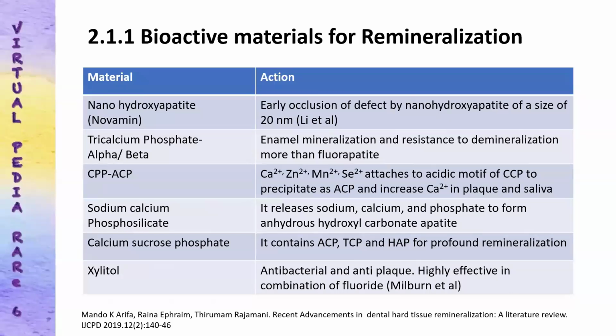The other materials which are helpful or potent for remineralization are nanohydroxyapatite, tricalcium phosphate in alpha and beta form, CPP and ACP, that is casein phosphopeptide and amorphous calcium phosphate, is the potent material for remineralization of the demineralized tissue. The unique property of CPP helps us to create a reserve of ACP ions, and it absorbs calcium, zinc, manganese, and selenium ions in a large amount. Whenever there is drop in the pH, these ions are released and it increases the calcium in the plaque and saliva. The supersaturated calcium and phosphate in plaque and saliva helps us to have remineralization of the tissues.